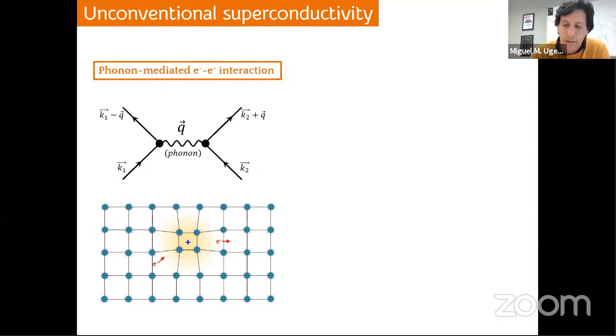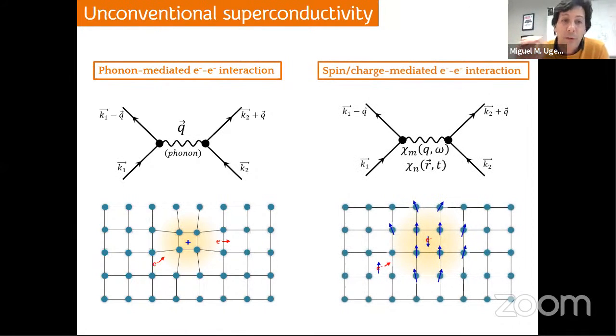But you should note that this is not the only mechanism possible. And that's what we refer to by unconventional superconductivity in general, right? So any mechanism for the Cooper pair formation that is not driven by phonons. For example, it's well known now that despite the repulsive Coulomb interaction, the effective electron-electron interaction can become attractive for electrons in certain space and time regions, being mediated by a spin or charge. So in this case, the pairing glue could be the spin or the charge. In particular, the role of the spin is quite important, because many different unconventional superconductors are believed to be mediated by spin-spin interactions.